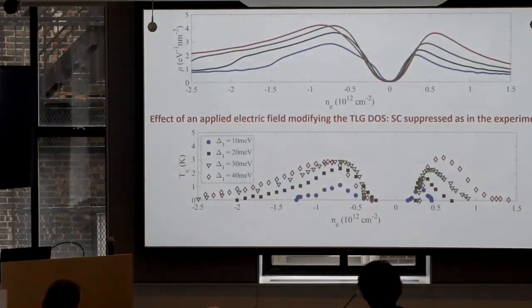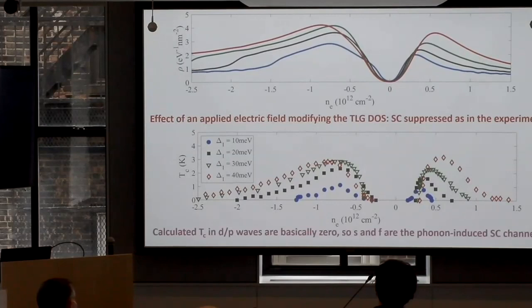And then we calculated how electric field will modify things. As you know, electric field changes the band structure. We can calculate it. So these are various gaps that electric field introduces, and eventually superconductivity should be suppressed. And some of these things we did because experimentalists did it, and it agrees with experiment. It's suppressed by the electric field. Okay?